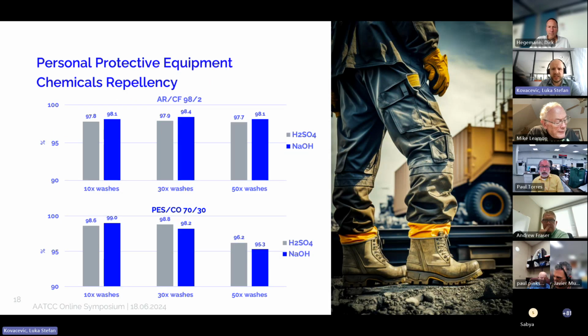We now also have a significant number of customers who are producing personal protective equipment with chemical protection using Eco Plus. Surely solvent-like test chemicals like xylene or butanol cannot be repelled by this fluorine-free chemistry, but you can see that, for example on aramid, concentrated sulfuric acid or concentrated sodium hydroxide solution can be repelled quite effectively according to the chemical repellency standard, and this applies even for a high number of industrial washes. After 50 washes here, you can see that we still have a repellency factor of 97, 98. On polycotton, the durability is a bit lower, but still above the 95% range in this case.